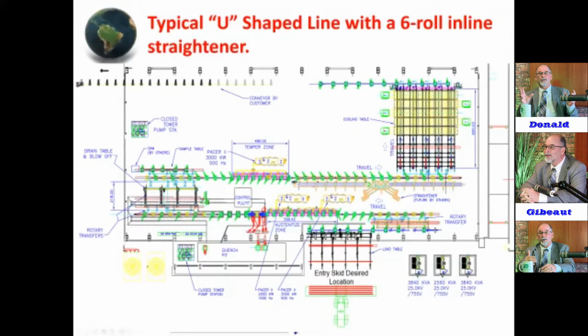We usually like to have a couple power supplies on each one so we can take an infrared reading in between them and adjust the second power supply as needed. And typically, if you're up north in Canada, these pipes come in with a lot of snow on them and have been sitting out in the cold. You can go through this austenitize, and in that second unit, you can adjust for that with a 0 to 10 or 4 to 20 milliamp or step control of the power. And metallurgists love it because of the ability, if the resistivity or the chemistry changes on the infeed between different manufacturers of the pipe or different batches of the rolls made to form the pipe, they can compensate for it here.